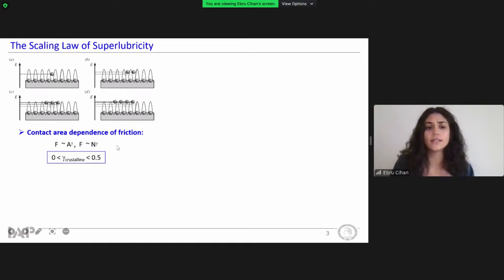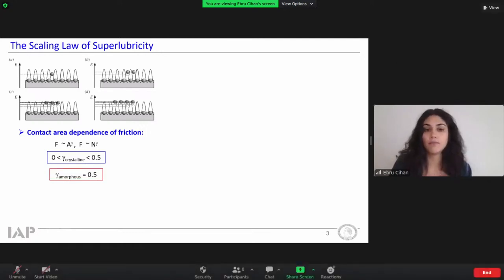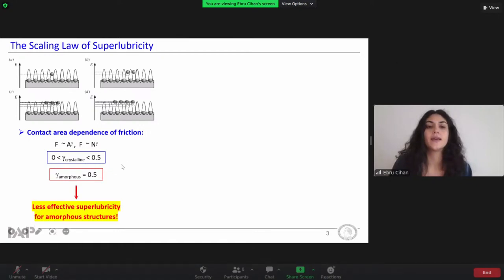So for well-ordered crystalline nanoparticles, this scaling factor gamma is calculated between 0 and 0.5, depending on the shape of the particle or the level of the commensurability between the surfaces. For randomly ordered amorphous nanoparticles, this gamma should be well-defined as 0.5. And this clearly indicates that less effective superlubricity is expected for amorphous structures.